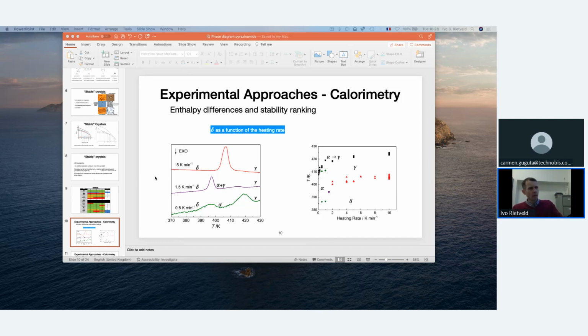So that is for the different crystals. Now, a bit more precisely looking into the alpha to gamma transition, I showed already some results of this. Here is the peak of the alpha to gamma transition. It was also studied in these two other papers that I showed to you quite extensively, and they already saw that as a function of the heating rate, this went down. But as you can see, it is just impossible to put a finger on this actual transition temperature.